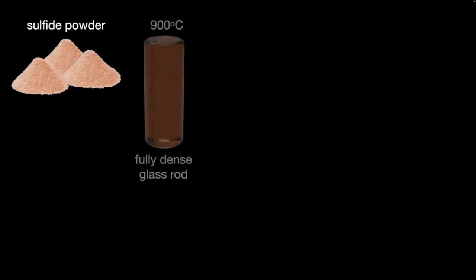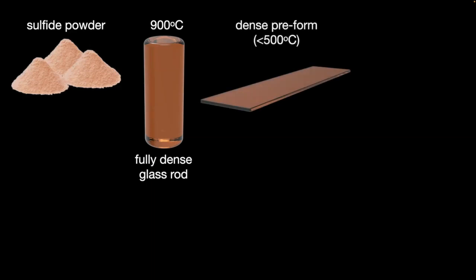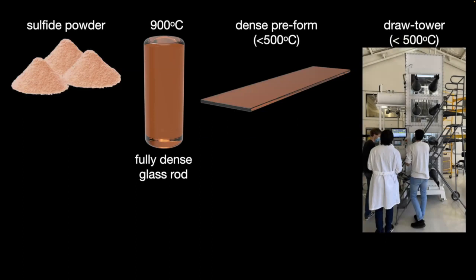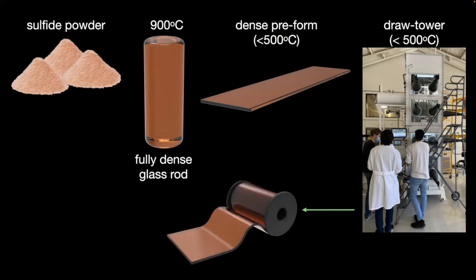So let's compare and contrast that to what we do for polycrystalline ceramics. Here we take the raw material sulfide powders, and in a single step, by heating that up above the melting temperature, we produce a fully dense rod, hopefully with no bubbles or inclusions. And then you start processing that rod. The next step would be making a preform if you're going to draw thin glass. That preform has to go into some type of draw tower. That's actually the tower operational in Berkeley. And then from the draw tower, you produce this continuous ribbon of thin glass sheet, which is the basis for building the rechargeable lithium metal battery.